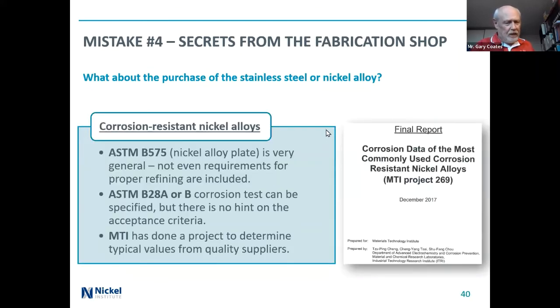With nickel alloys, it's actually an even worse situation, and we're running into problems with certain suppliers who don't know how to make it properly, but they can easily meet the ASTM specifications. So for example, B575 is one for most corrosion-resistant materials. They don't even require any aspect of refining, and there are reasons for that. I won't go into it. You put a corrosion test on it. There are standardized tests that you can do, but there's no acceptance criteria.